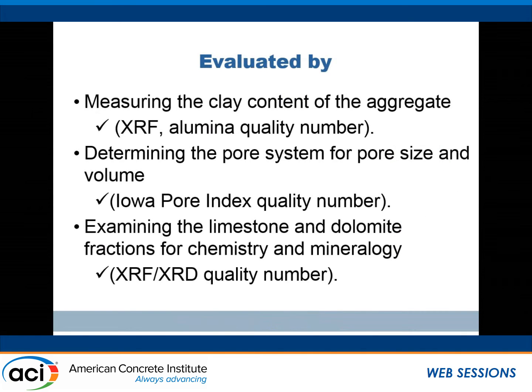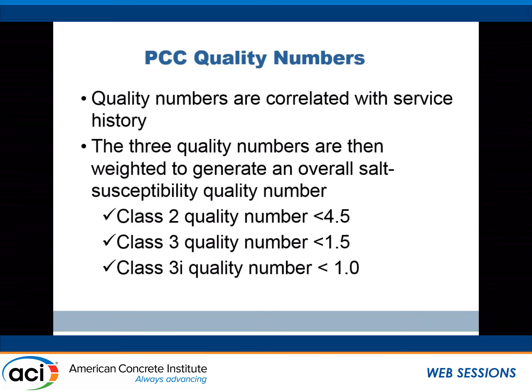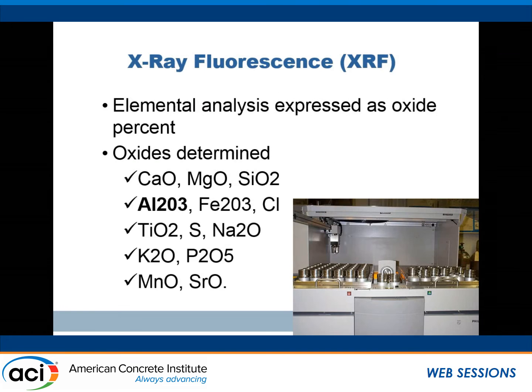All right. So the three parameters that the DOT uses, it's not just the size. They look at the clay content of the aggregate. They look at the pore size, and they also look at the limestone dolomite balance. So how much magnesium do you have in the system? And they come up with what they call quality numbers. And they do a weighted system on which quality number matters the most depending on where it sits in that limestone dolomite scale. And I'll get to that a little bit later.